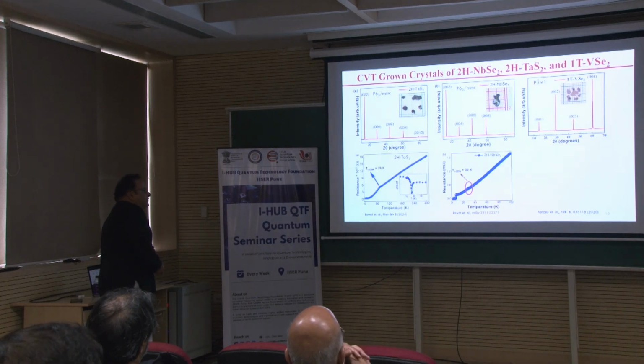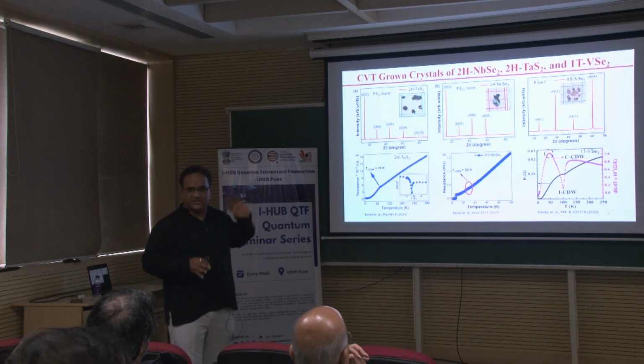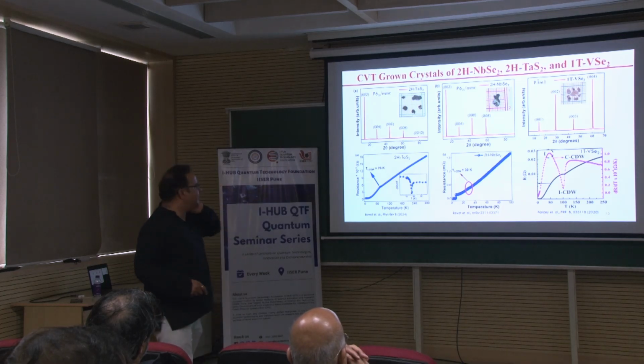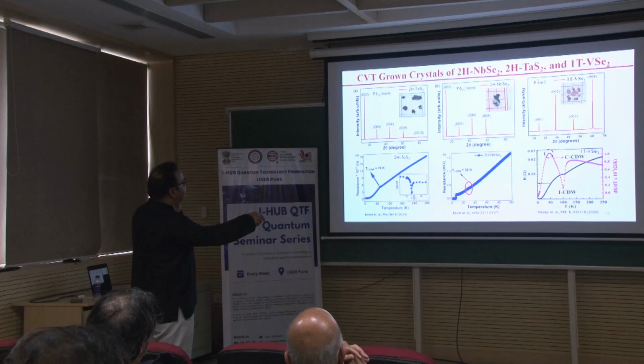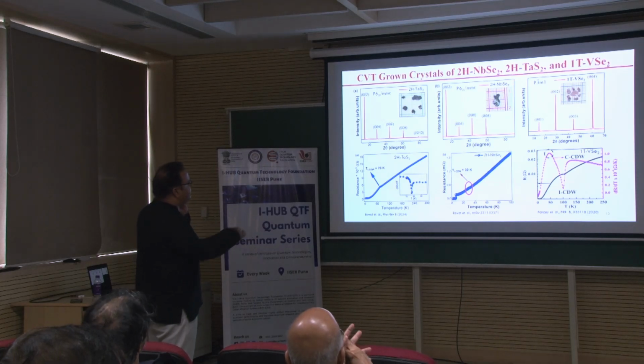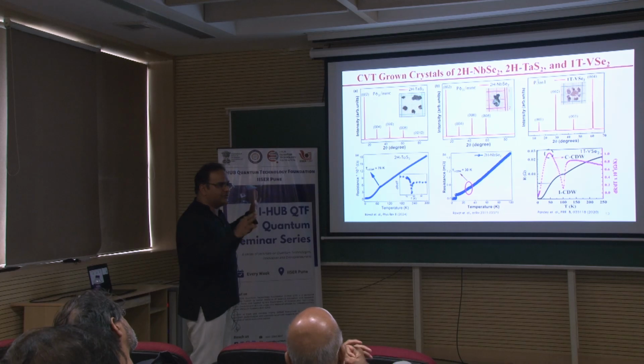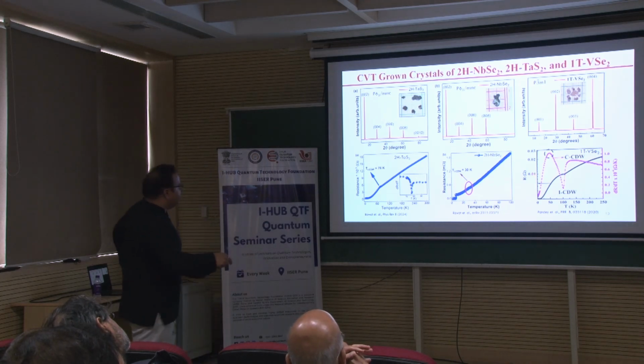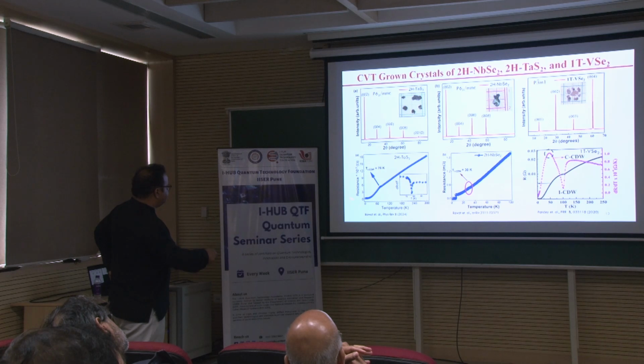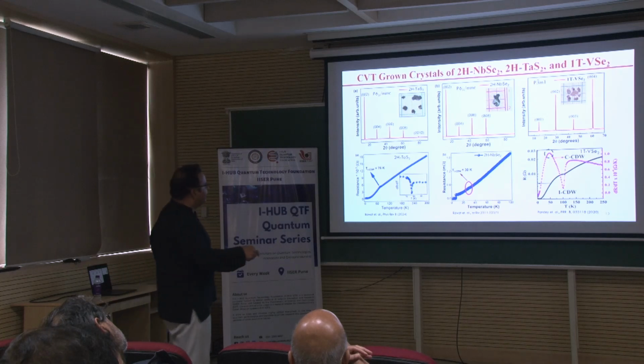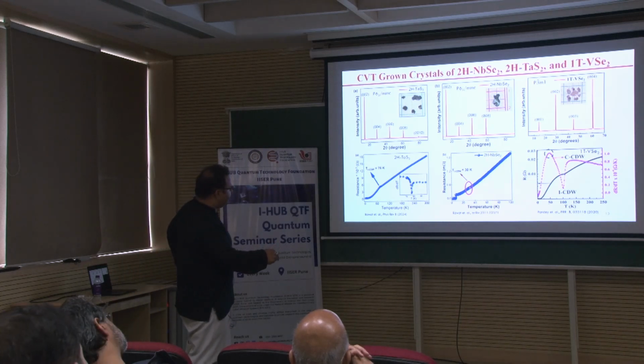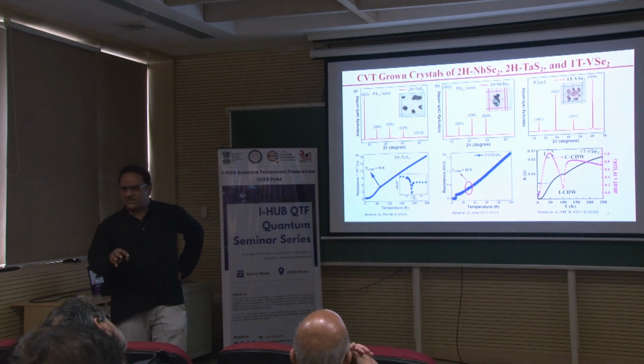I do not want to discuss much on the other characterization because my focus is on the Raman, but as I mentioned, tantalum sulfide, niobium selenide and VSe2 are the materials which show charge density wave and they are unique, so I club them together. Now, we will talk about the resistance as a function of temperature. For tantalum sulfide, right at 76 Kelvin, it shows an incommensurate charge density wave. Niobium selenide shows charge density wave at 30 Kelvin and superconductivity at around 9 Kelvin or something,